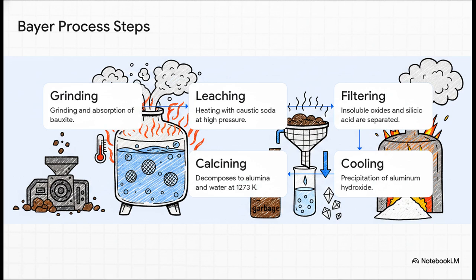Eventually, the mixture is cooled down, which allows pure aluminum hydroxide to crystallize right out. And for the final step, it's dried and calcined, meaning it gets blasted with heat at 1273 Kelvin to decompose it into pure alumina and water.